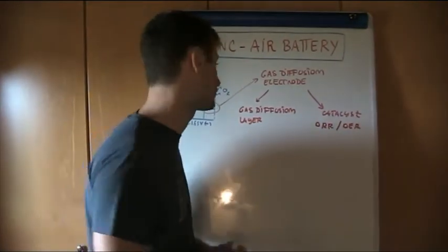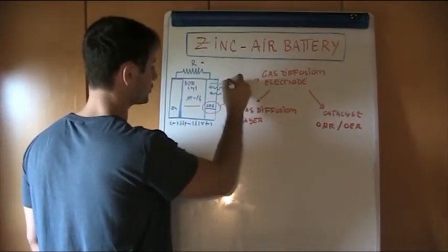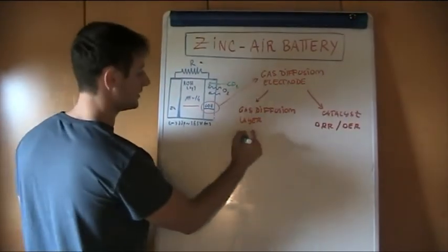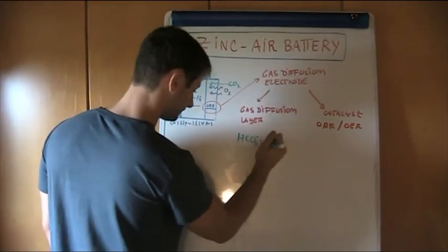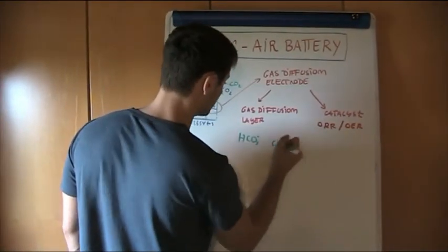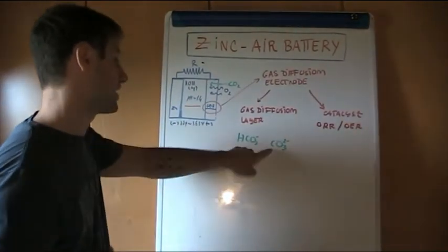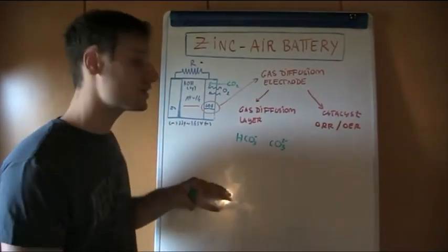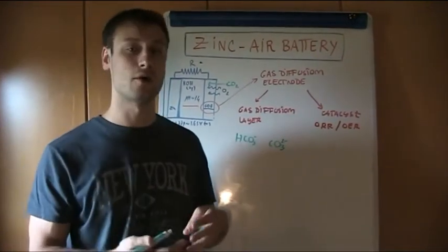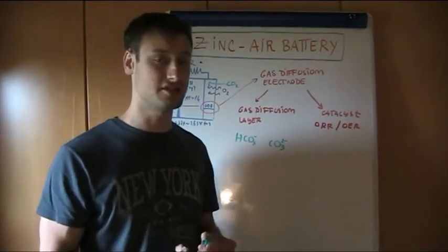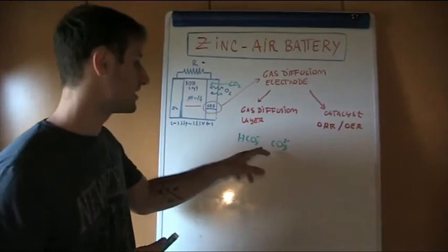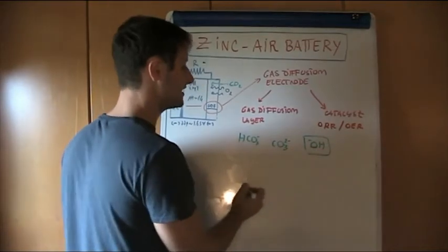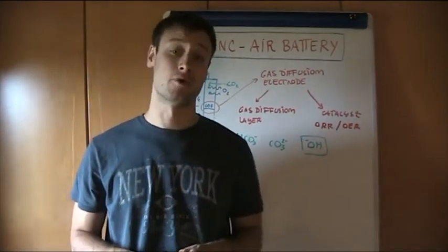On the other hand, we have already described this quite precisely in the first lesson, speaking about the metal-air battery. We have the diffusion of CO2 from outside, since CO2 is also present in the atmosphere, which can create carbonate and bicarbonate through interactions with water. These are able to promote the clogging of the pores, and when we have a high concentration they may generate sedimentation. But more important is the fact that these ions are less mobile with respect to hydroxide, and so we are basically decreasing the performance of our battery.